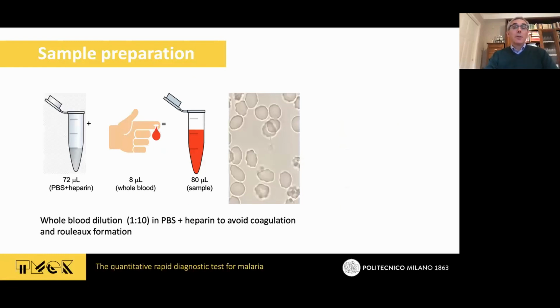And now, what about sample preparation? As I told you, it's quite simple. We just take 8 microliter of whole blood, we dilute in heparin PBS, we create the sample, 80 microliter. We take now 70 microliter, and the fact that we're using heparin and PBS creates a nice solution in which you don't have coagulation and rouleau formation, which is obviously what you need. You want to keep the integrity of each particle in order to attract it and measure it.